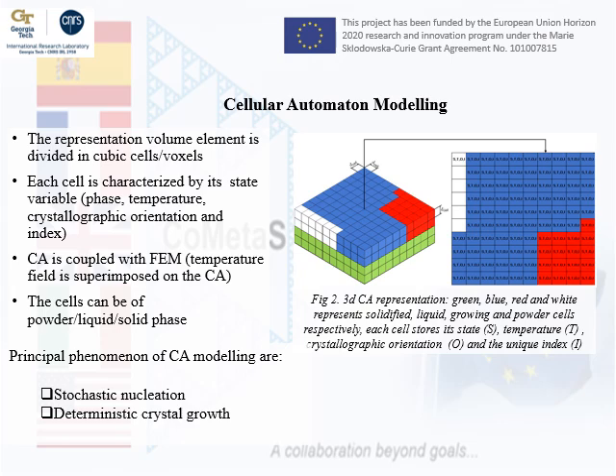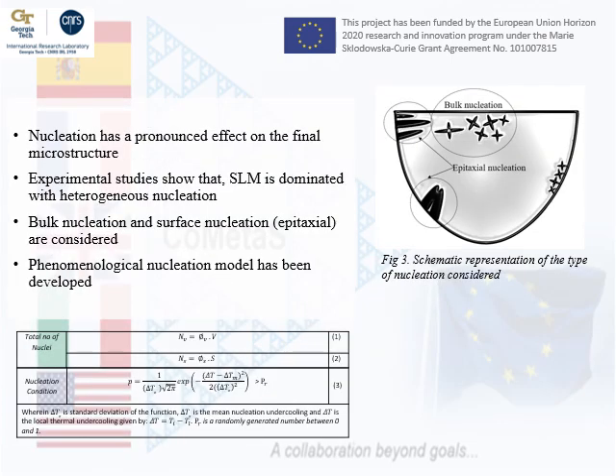To do this in the model, we need to separate these two different mechanisms. On one hand, we need to consider nucleation, and on the other hand, we also need to impose a growth model for the crystal growth during solidification. The nucleation model is usually stochastic in nature, and the reason is that nucleation is a very complex process. So we usually consider two different nucleation mechanisms, which are also observed experimentally in additive manufacturing.